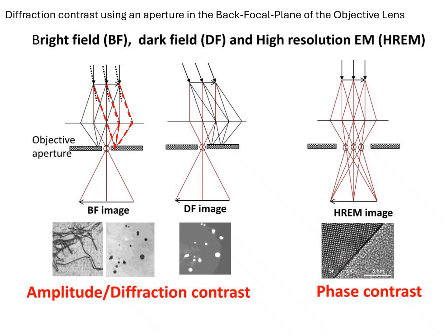So in this configuration, we see a bright field image. We look at the electrons directly passing through the crystal, and we throw away anything which is essentially diffracted, scattered off at one angle or another. And that shows up as a deficit, a dark image in an otherwise white background.